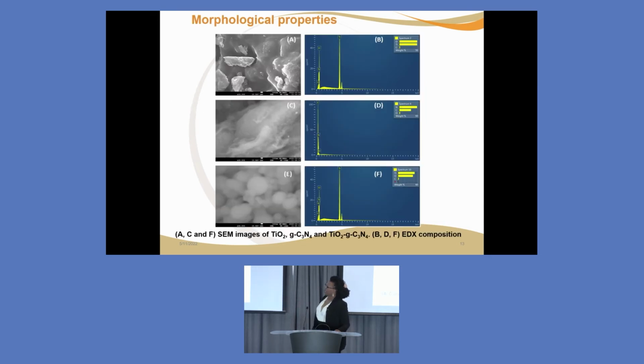So in this case, we have done some characterization whereby we were monitoring the morphology. So in this case, we are monitoring the particles on top. So we are seeing that we have A, C, and E. So A, C, and E, meaning that we have titanium oxide, we have graphitic carbonitride, and we have the composite material. So you can see that from here up to the composite material, we have changes in the shapes. So that means that if we have changes in the shapes, it means that we have formed our composite material.